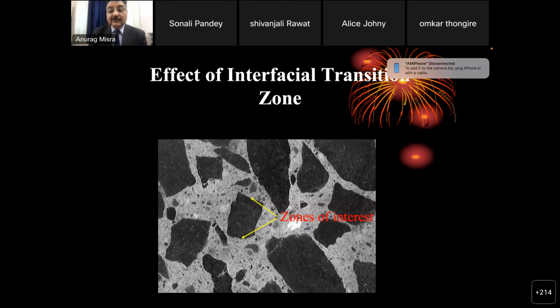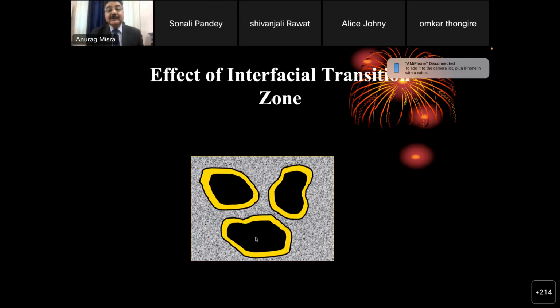This interfacial transition zone also has a great effect on durability, especially when it comes to the cover zone properties of concrete. So let's assume that there is an aggregate, and this is the cement paste. It has been observed that if we are unable to control a few parameters, this area, shown here in yellow color, which we call the interfacial transition zone, comes out to be more porous compared to the main matrix. So the attempt has to be to control, for a particular mix, the parameters which make this transition zone more compact and as uniform as the remaining cement matrix.